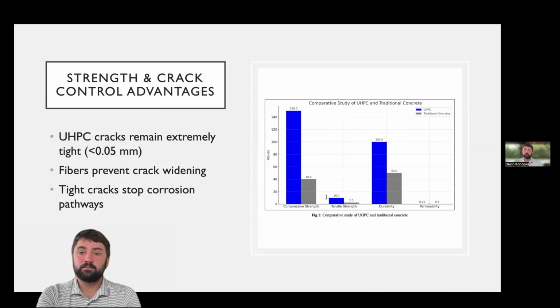Another big contributor to durability is the crack control. UHPC doesn't just have higher strength. The cracks that do form stay incredibly tight, typically under 0.05 millimeters. The steel fibers disperse throughout the mix and help bridge micro cracks, preventing them from opening wider. And that's crucial because wide cracks are what allow water and chlorides to enter and start the corrosion process. UHPC cracks are so small that they don't create those pathways at all. A key thing to remember is that UHPC protects itself by controlling the cracks before they become a durability problem.